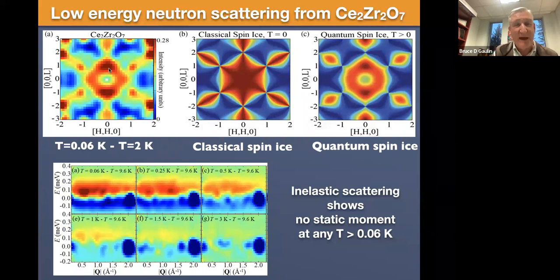And we get this pattern that you see over here in the top left, which is kind of a snowflake-like pattern. We describe it as a snowflake-like pattern, but there's something that looks like a ring around Q equals 0, although it's not an exact ring. And then it has these extensions that go out along 00L directions and out along 111 directions. And actually, it bears some resemblance to the expectations of diffuse scattering in classical spin ice.